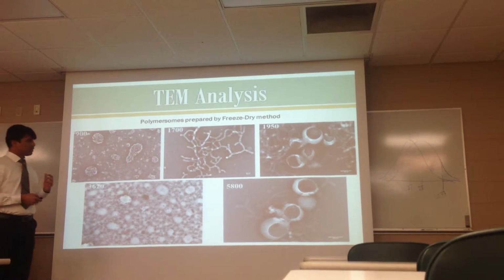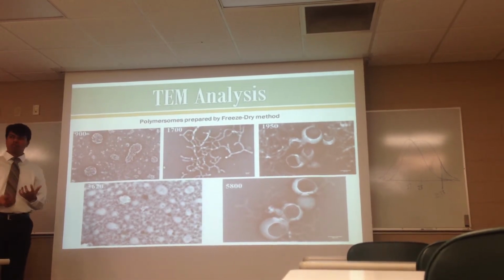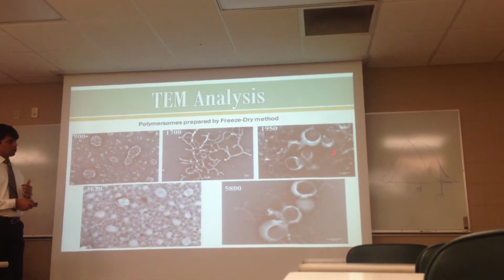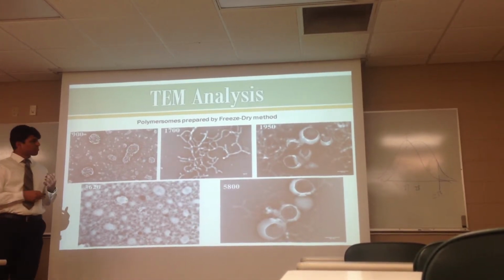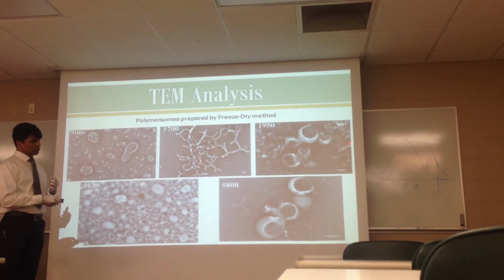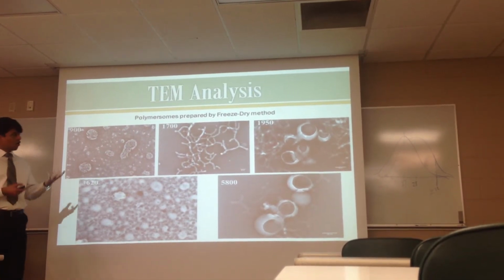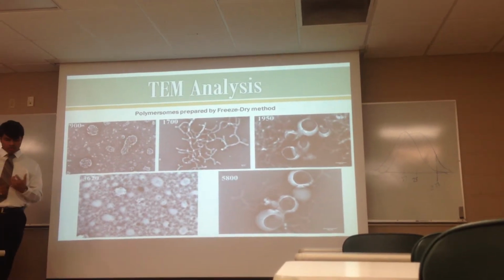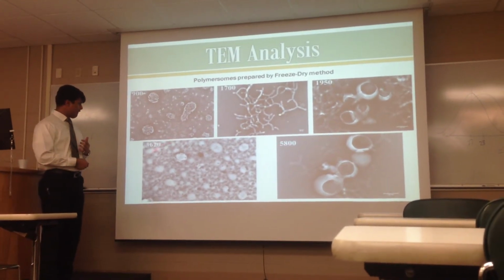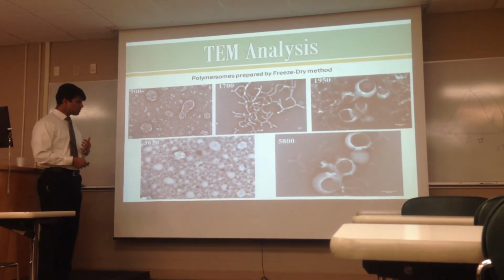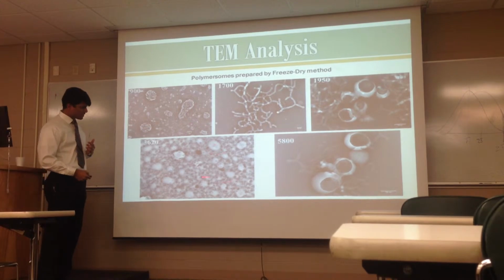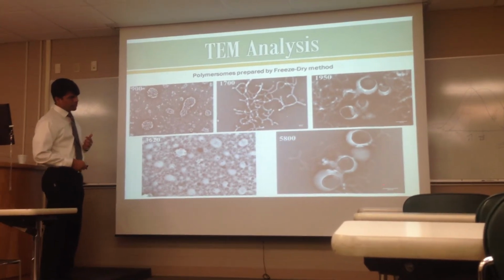With 1700, the samples were mostly long worm-like, bicelle structures. In 1950, although we noticed some vesicles getting formed, most of the sample was long bicelles and worm-like structures. The only two samples where the majority of polymers were forming vesicles were the 5800 and 3620 samples. And as you can see, they formed vesicles with sizes around 100 to 120 nanometers.